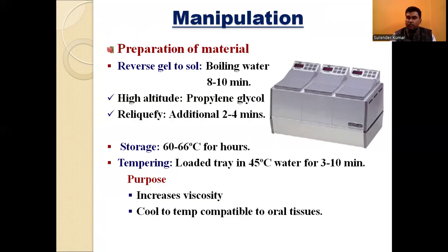Now, after that, the first compartment is the boiling or liquefying compartment. The second compartment is known as the storage compartment, whose temperature should be 60 to 66 degrees. You can store it for hours. And then the third compartment is known as the tempering compartment.